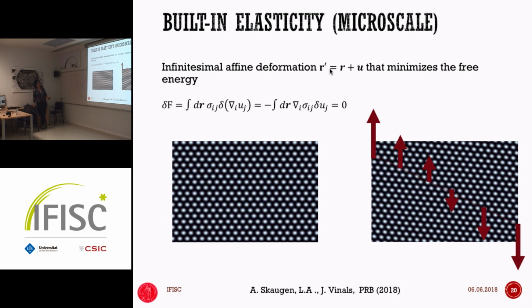Okay, so now in order to study mechanical deformation, we have to think of deformation. How do we apply a deformation field? So we start with a simple case where we have an affine deformation U that takes us from an unperturbed system to a deformed system. This is the case where I just apply a shear in one direction. But it's a smooth deformation and it's small. So the gradient of this deformation field is assumed to be quite small. So we are in the regime of linear elasticity.